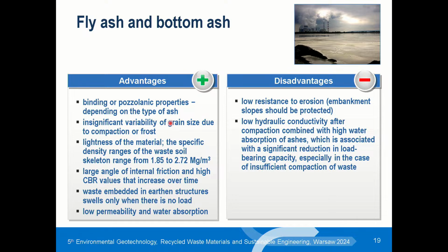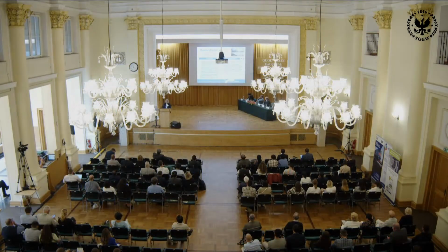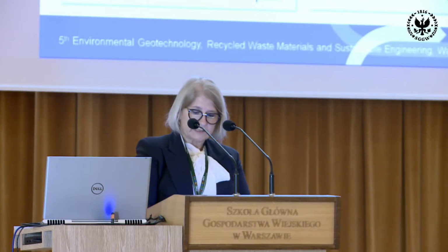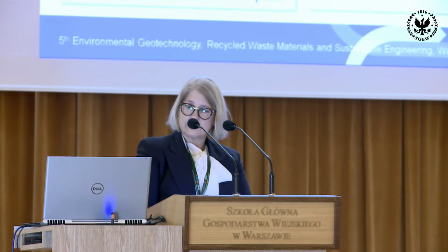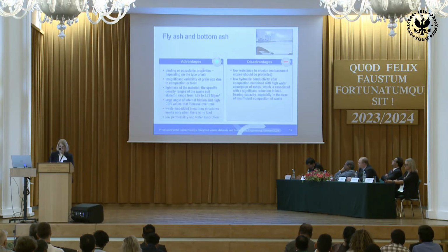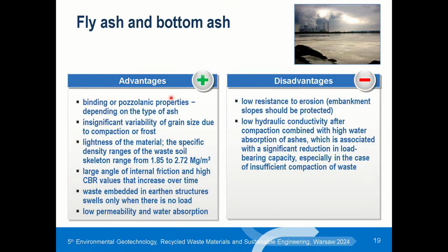You can see that fly ash and bottom ash have many advantages, such as binding and pozzolanic properties, insignificant variability in grain size due to compaction or frost, lightness of the material, large angle of internal friction, and high CBR values that increase over time. Waste which is embedded in the earth structure swells only in the absence of total load. They have low permeability and water absorption, but it can be advantages or disadvantages. It depends on the application.